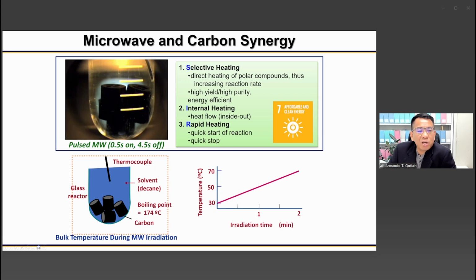So here in this video, microwave is applied in pulse mode. When we say pulse mode, the microwave is on for only about 0.5 seconds, and it's off for 4.5 seconds. The solvent is decane, which is relatively microwave transparent. It doesn't absorb microwave. And the thermocouple monitors the bulk temperature. That's actually the temperature of decane. The boiling point is 174 degrees centigrade. The carbon material is in decane as well.